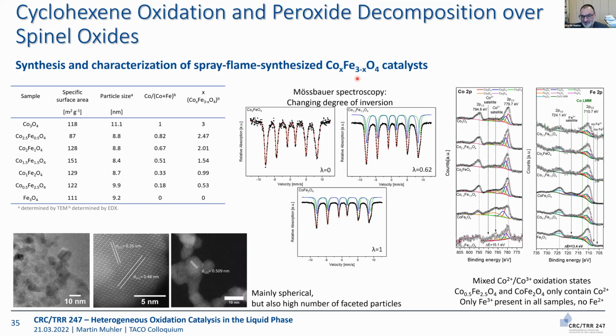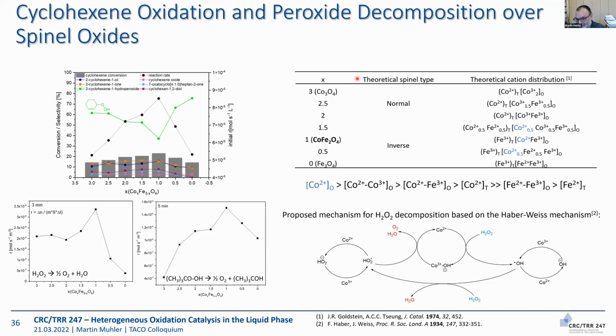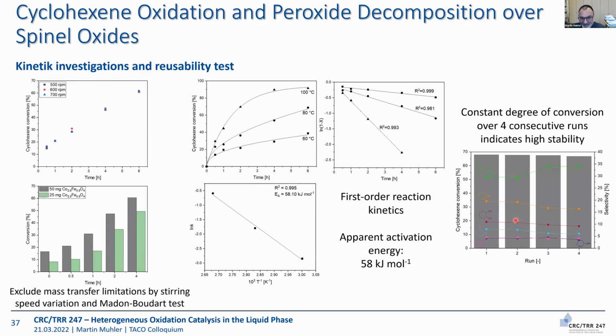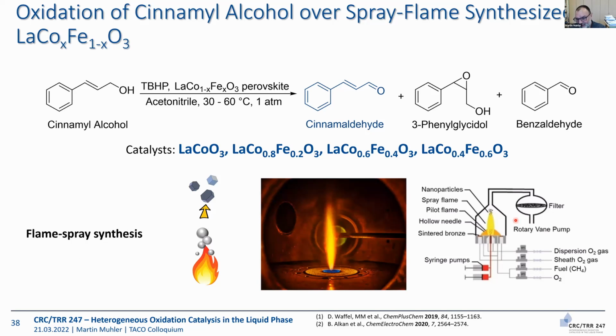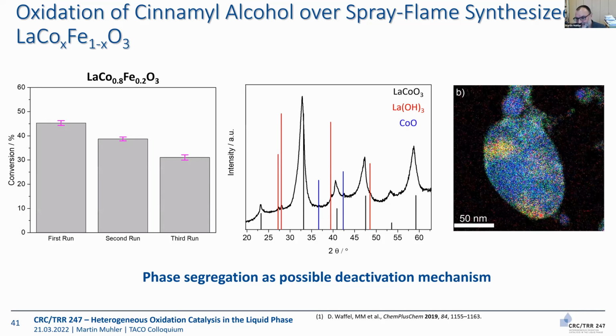Now I think I have to jump to the end with a few more comments. We made the same experiments also with substituted spinel catalysts. Peroxide decomposition actually has old mechanisms, and that is really Fritz Haber who is in here. Although you get nice formal kinetics, I have to jump here, this is now a perovskite. You realize that the structural integrity is in the end no longer given. It is iron substituted lanthanum cobaltite, a complex system. It deactivates after every catalytic experiment, and EDX tells you that the system is disintegrating, and that is of course a major drawback. You do your best during synthesis to achieve perfect mixing, phase purity, homogeneity, but during reaction the system may deactivate by segregation.